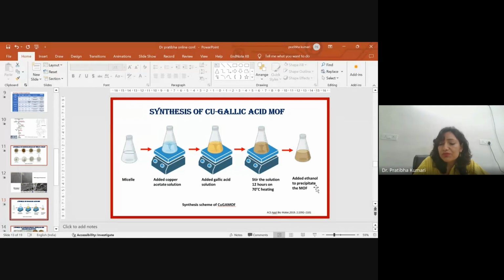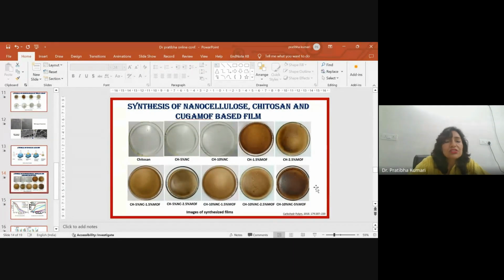But nanocellulose does not make a very good quality film. So to have a better material to make a film which is quite stable, we use chitosan also, because chitosan is a film forming material. So we use chitosan as a base material, and then we mix nanocellulose and the gallic acid MOF into it. And then we prepare different types of films.